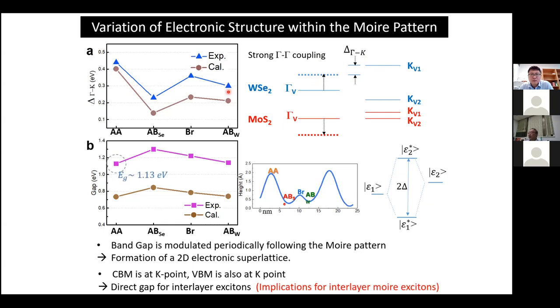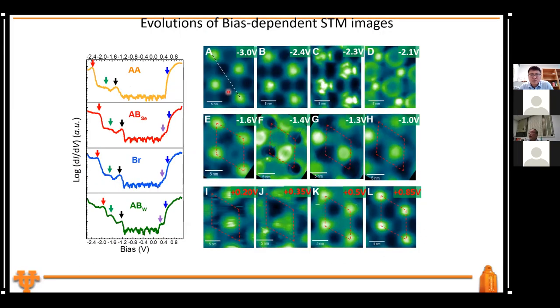And then we further prove that even after the interlayer coupling, this hetero-bilayer remains a direct gap material. And so you can also map out the whole 2D electronic structure. Unfortunately, at the time, we really cannot compare with the DFT because DFT cannot really calculate such a large unit cell. But the tunneling spectroscopy showed this very pretty 2D electronic superlattice.